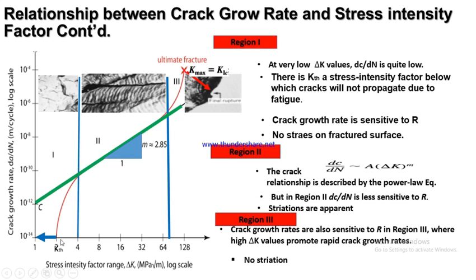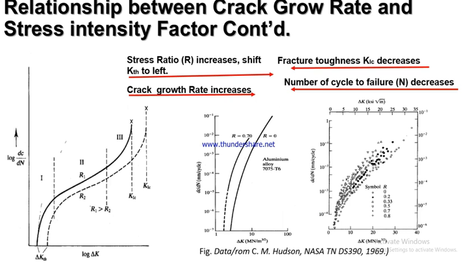After you have exploited the material all through this profile to this particular final fracture point, we can see from here that the ultimate fracture that took place in the material occurs when the maximum stress intensity factor is equal to the fracture toughness of the material. Immediately the fracture toughness equals the maximum stress intensity factor, the material will definitely fracture. At that point, the strength of the material will not be able to withstand the cyclic stresses. I forgot to explain this to you.